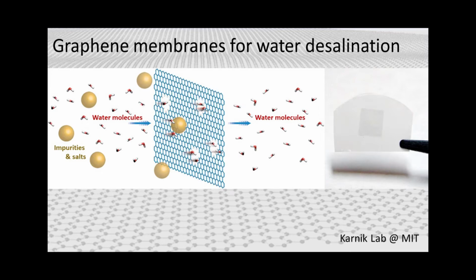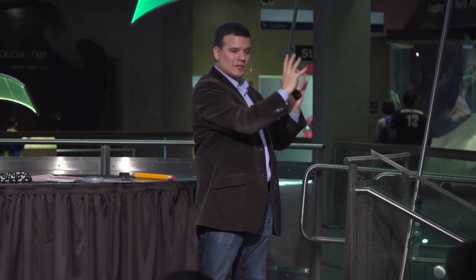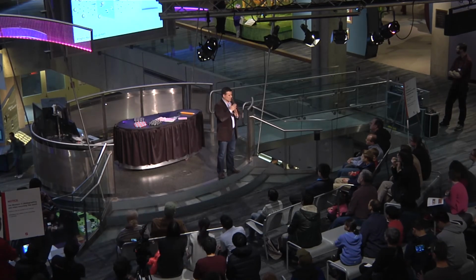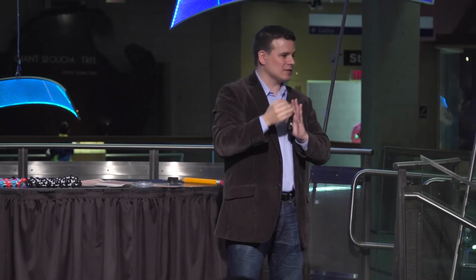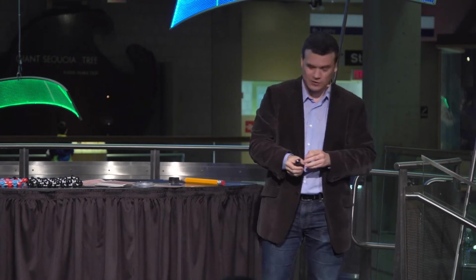Now, one of my favorite applications is one that one of my colleagues at MIT, the group of Rohit Karnik, is doing. They are using graphene as desalination membranes. Graphene is so thin, actually, the hexagons in graphene, nothing can make it through. But what you can do is make very small pores, very small holes on the graphene, and use it to separate dirty water with salt and impurities from clean water. You can make this water flow through the graphene, only the water molecules make it through, none of the dirt, none of the salt. And because it's so thin, it's very efficient at separating this water. So people believe that with graphene membranes, we will be able to desalinate water at a fraction of the energy and cost of other technologies. And this is something that is currently under investigation.